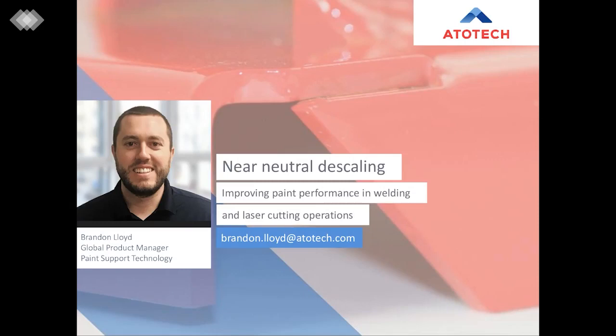What is the application time for the neutral pH descalers? The application time really can vary from one application to the next. This depends on the amount of oxide scale that needs to be removed, as well as the method of application, and by this I mean whether it's spray or immersion. Of course, longer application times should offer improved scale removal. But what we've seen in some of our evaluations is that increasing the temperature has shown to offer even more improvement on the weld scale removal rates as compared to longer application times or increasing concentrations.